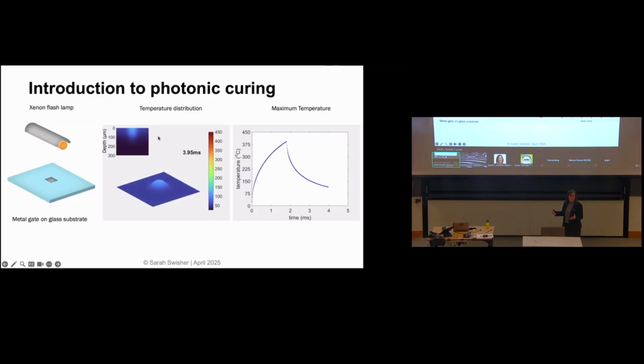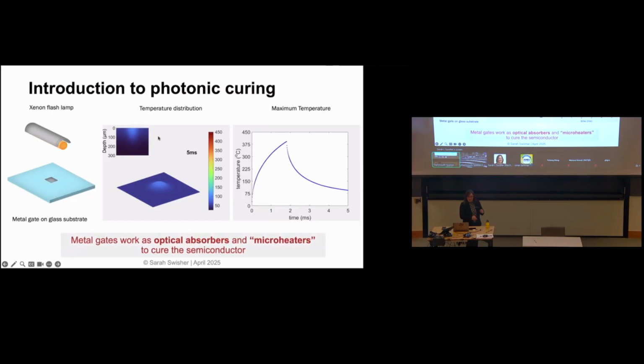temperature decreases again. So this is what we call a non-equilibrium thermal process, because the whole substrate is not reaching the same temperature. You're actually getting localized heating in the region of that metal absorber, and you're not getting heating of the whole substrate underneath. Right? So this is what makes photonic curing so unique and so useful, because we can just heat the region of the material that we want to, and we can keep the heat away from the other regions.